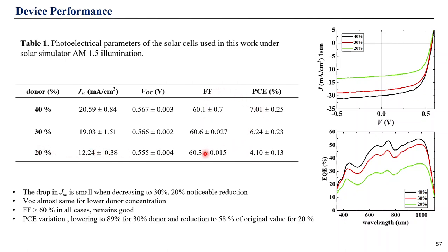While fill factor remains pretty much the same, VOC slightly decreases, but short circuit current drops significantly. And that correlates well with EQE spectra, which we also measured. So we need to understand what's actually going on and what's the reason for this. For that, we need to systematically address photo generation, recombination, and extraction.